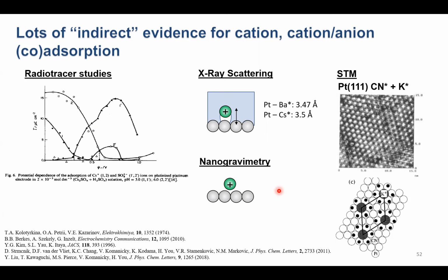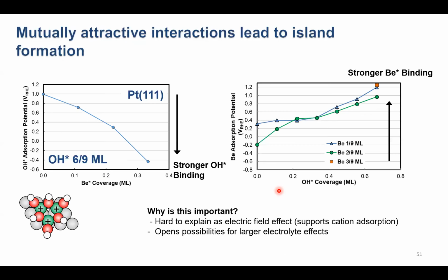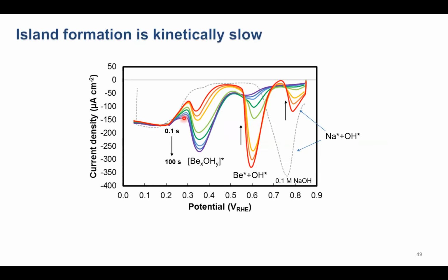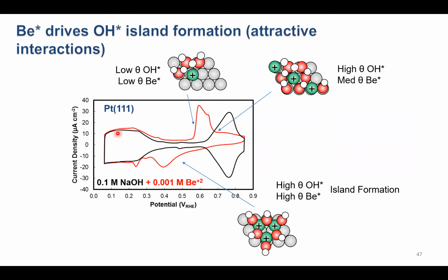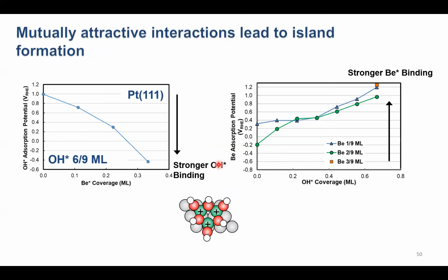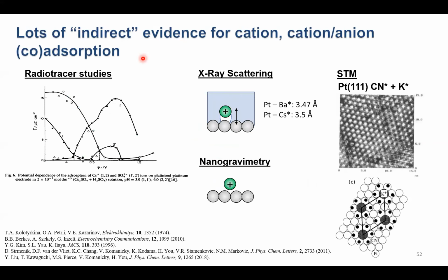First, I want to mention that some people tend to think that cation-specific adsorption is impossible because we have never observed direct experimental evidence for cation adsorption. What do we mean by that? We've never seen an adsorption peak in a CV that corresponds to the adsorption of an alkali metal cation. We see hydrogen adsorption, hydroxide adsorption. We see the effects of a cation, but we never see a peak that we could really assign to being due to the cation.